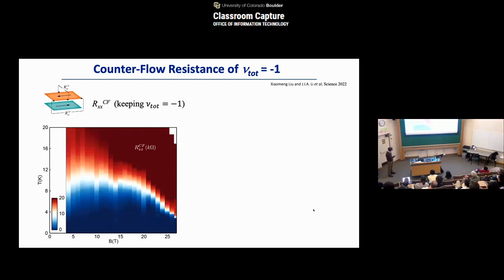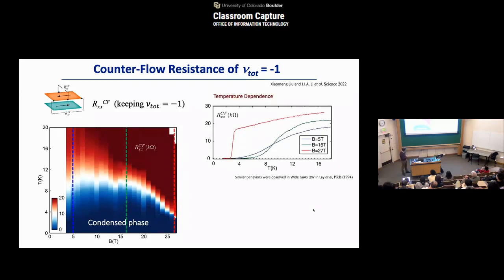So what you see here in the color map, which shows the counterflow resistance, is a nice phase transition diagram, right? This is similar to the phase diagram I showed you before. It turns out that the distance between the magnetic excitons is basically controlled by the magnetic field, right? So for this condensation state, as I change the magnetic field, I can change the density of the magnetic excitons. In fact, I can show you, at a fixed magnetic field, how the transition is changing from low magnetic field to high magnetic field. The transition behavior from the uncondensed to the condensed state is rather changing.